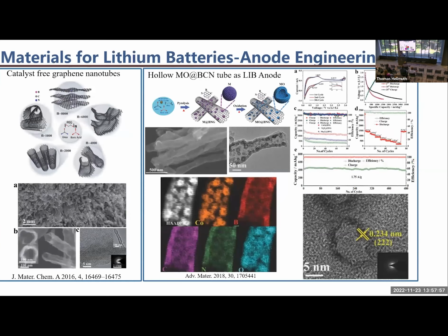So let's have a look at the anode materials, which I have been working on previously. In this work, for example, I wanted to address two issues. One is to improve the efficiency, and second is to improve the cyclic stability. Now, one of the key issues with graphite is that it has lower capacity, 372 milliampere hour per gram. If we can introduce transition metals, they can perform very well. They can give very high capacity, but they lose performance very quickly because of aggregation, because of pulverization, volume expansion.